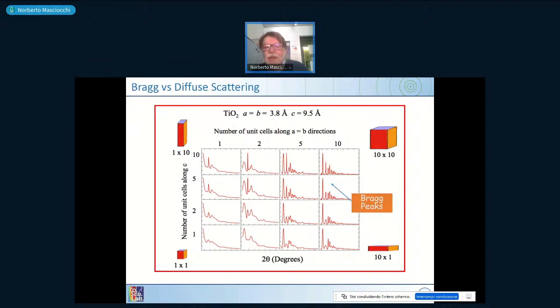Unfortunately, this is normally called Bragg peaks because you have no background, and this is called diffuse scattering. But it's nothing else than the same effect. This is a small nanoparticle, this is a larger nanoparticle of a single crystal. So what is normally called Bragg peaks is the total scattering with very little diffuse scattering. When you talk diffuse scattering, it's nothing else than total scattering, where the diffuse scattering or the background is wider or bigger or larger in intensity than the Bragg peaks. But everything is encoded in this so-called total scattering method, where the total scattering includes both Bragg peaks and diffuse scattering. So there is no distinction between these two different extremes.